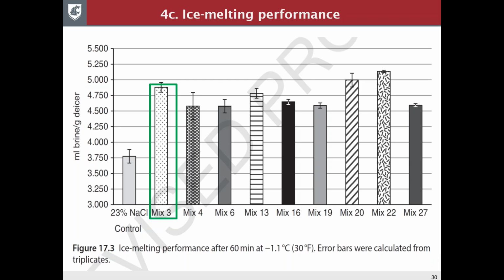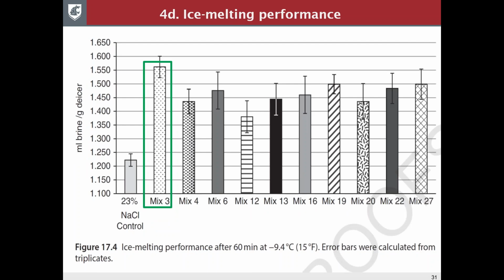You can see the ice melting performance at 30 degrees Fahrenheit is much better than the control, which is the 23% sodium chloride brine. I didn't show the data here, but it basically reached a level similar to 30% magnesium chloride. Now at 15 degrees, very similar trend. Mix 3 was much better than the salt brine control.